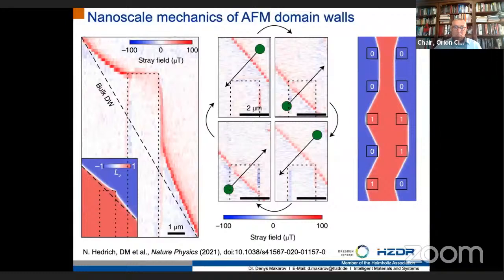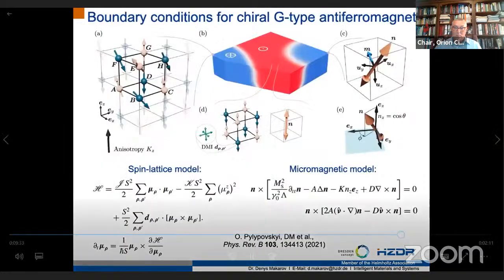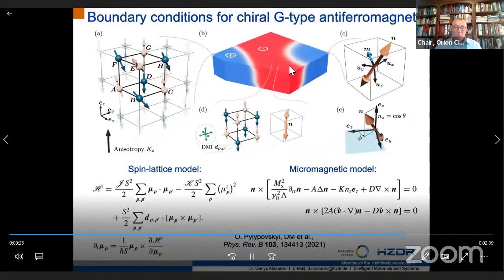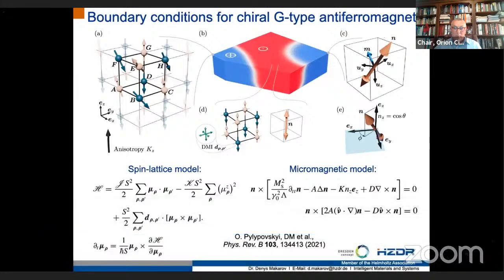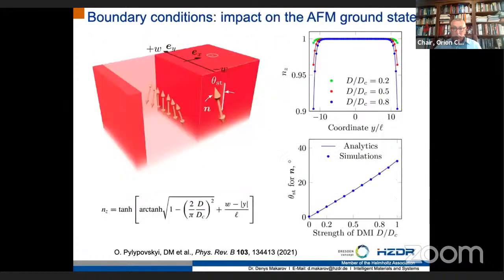The interaction of non-collinear textures with boundaries and with surfaces in antiferromagnets is actually very poorly understood even for three-dimensional antiferromagnets. In this case, Oleksandr Pylypovskyi made an effort to describe the impact of boundaries on chiral G-type antiferromagnets. In this case, the antiferromagnet has exchange, anisotropy and Dzyaloshinskii-Moriya interaction in the material. Now what is happening if you have the ground state? The ground state for the case when DMI strength is subcritical is a collinear antiferromagnet in the interior of the material.